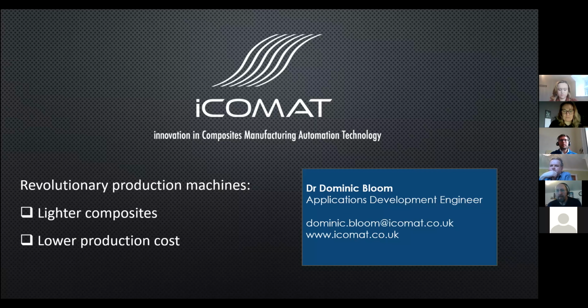The issue with thermoplastics in thermoplastic pre-preg is that you need quite a very high temperature to process them, and our heating system isn't really capable at the moment to handle that. But what we have done with thermoplastics is we've used commingled tapes, so it behaves like a dry fiber at room temperature, so we can shear it no problem. But then that needs maybe a secondary process to apply the heat and the pressure to get the compaction and consolidation you need. So these are things we're all looking into, and it's really customer driven. If somebody wants to use thermoplastics, then we're going to have to look at that more closely.